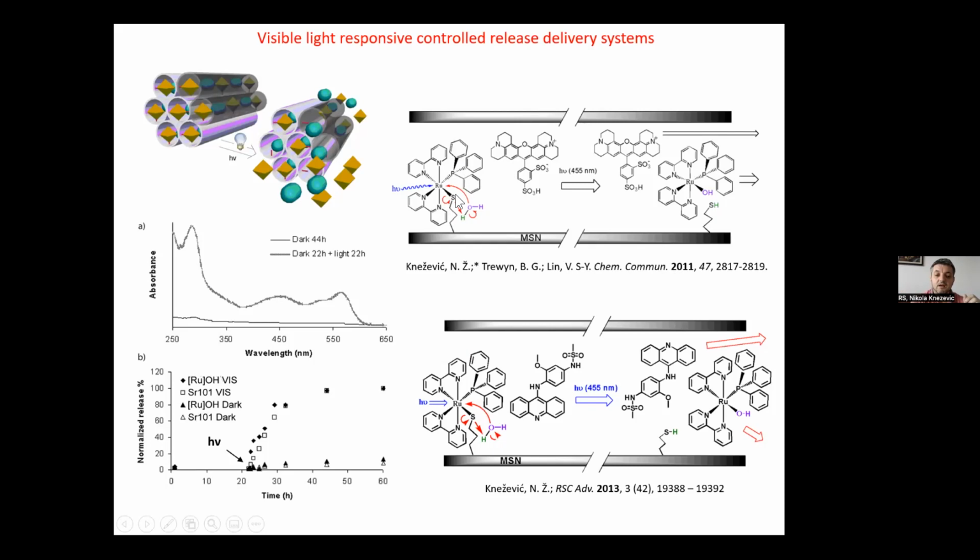And then this ruthenium-sulfur bond, a coordination bond, is being cleaved upon exposure to blue, visible light. So we just use regular LED light. And then you can see here the measurement of kinetics. After 24 hours or so, there was no release of either the ruthenium complex, because you can see these two peaks, about 200 something and 450, coming from ruthenium.